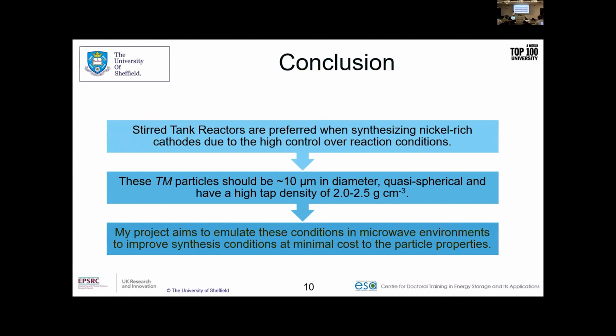And with that, I'd like to conclude, just to remind and emphasize the fact that in order to produce these sensitive nickel-rich cathode materials, we need a lot of control over the reaction conditions. And in order to do that, we use co-precipitation techniques in a stirred tank reactor, or if we can make a continuous stirred tank reactor, to form spherical particles that are approximately 10 micrometers in size with secondary particles, and a high tap density of around 2 to 2.5 grams per centimeter cubed. And we're going to hopefully use that, and I'll be able to replicate these microwave environments to make them a lot faster and reduce the cost as well.